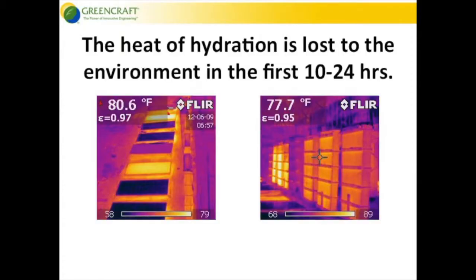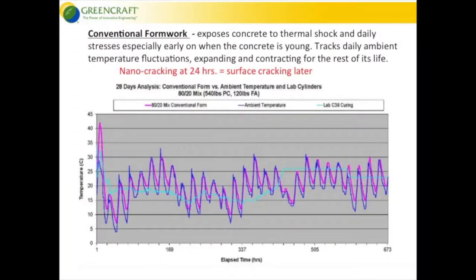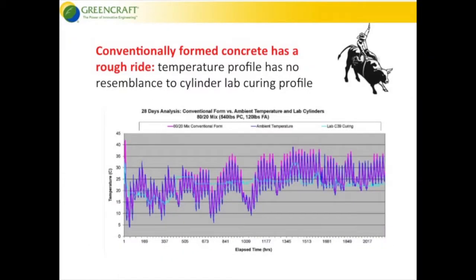So here are some infrared pictures of some of these forms, where you can see how the face of the conventional form is pretty much the same temperature as the concrete inside the form. And you can see the radiation of the heat escaping the form, kind of like you see in that chart. So a conventional form basically exposes the concrete to thermal shock and daily stresses, especially when the concrete is young. When you get the nano cracking at 24 hours, that's the surface cracking later. This is a 28-day chart. We fast forward to a 90-day chart of tracking all that temperature. Concrete in a conventional form has a rough ride.